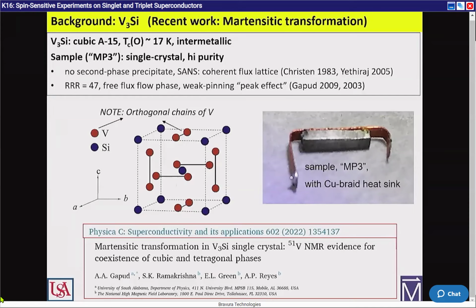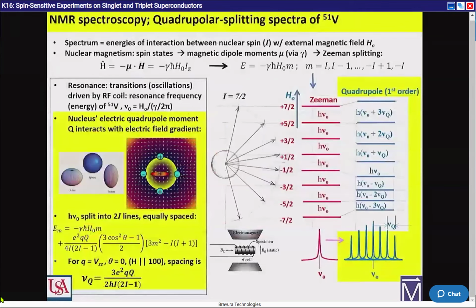Building on that success, we went on to T1 measurement to probe the electronic density of states, the gap structure. And the only note I will add for NMR is, as described previously, the nuclei have also a quadrupole moment that interacts with the field gradient of its chains. And instead of the 9 lines that you see with niobium, for vanadium-51 you have 7. And I'd like to add that the spacing is very sensitive to the orientation of this crystal.